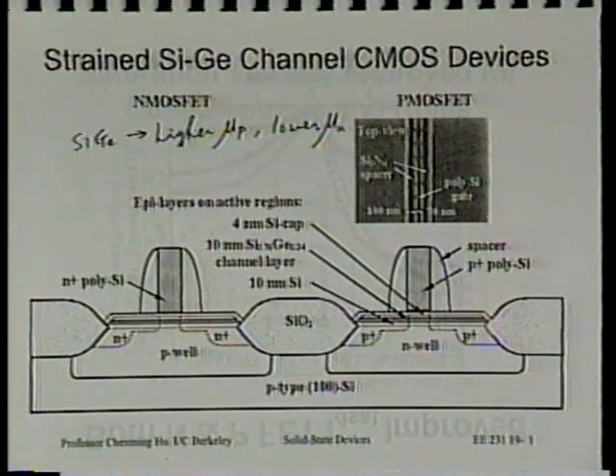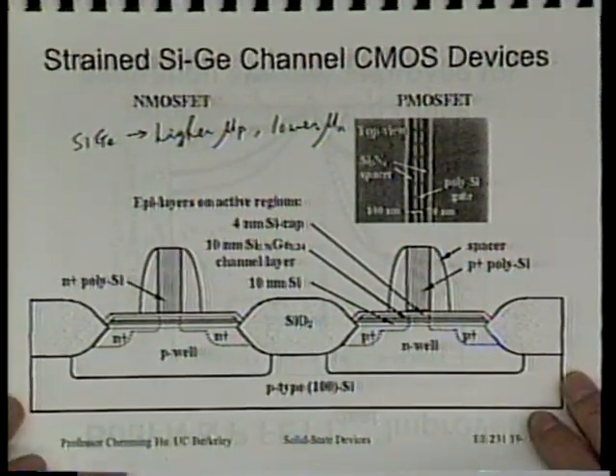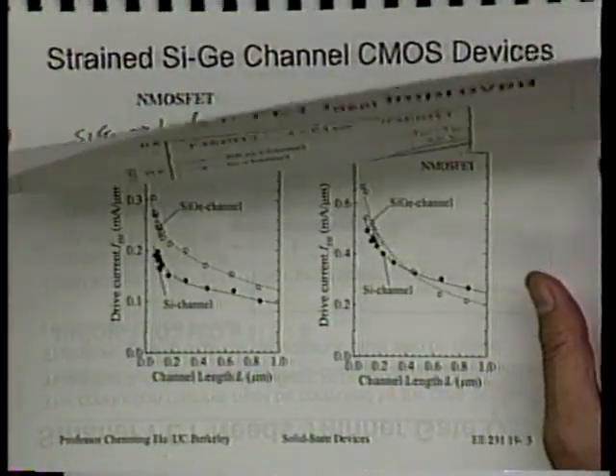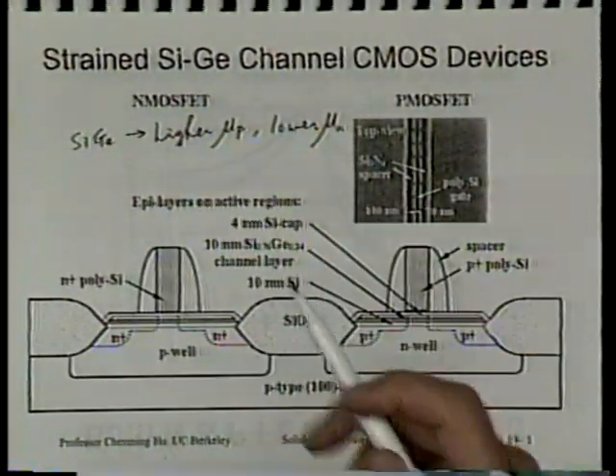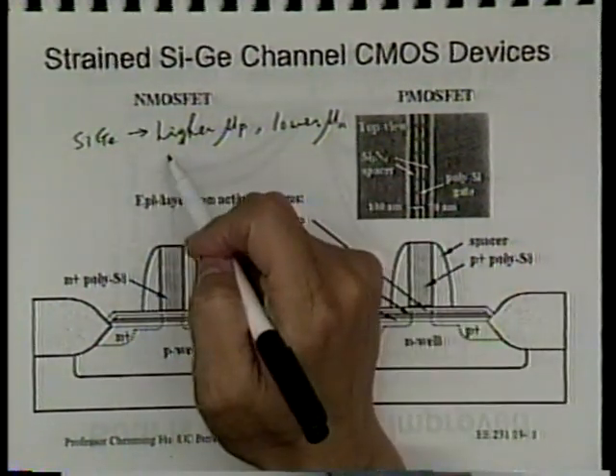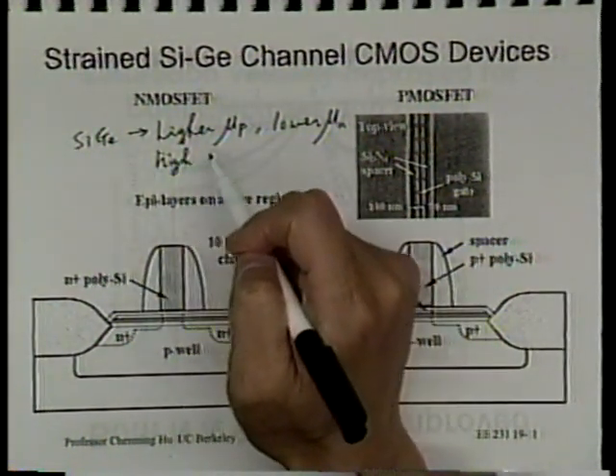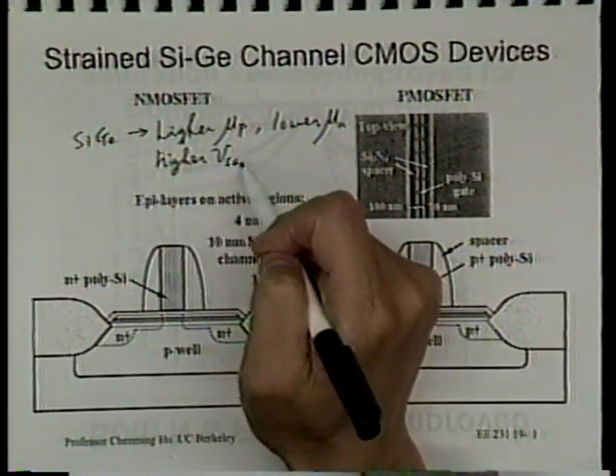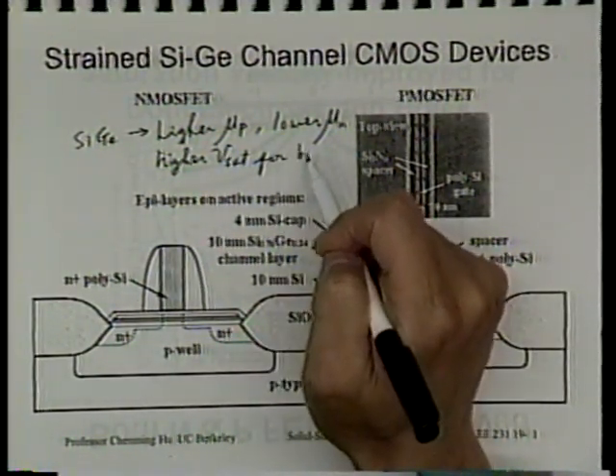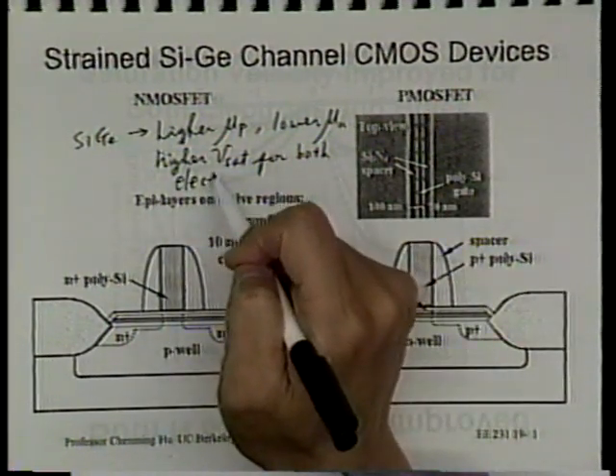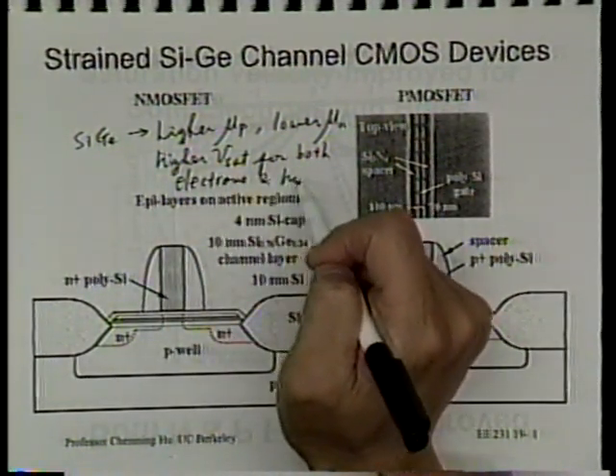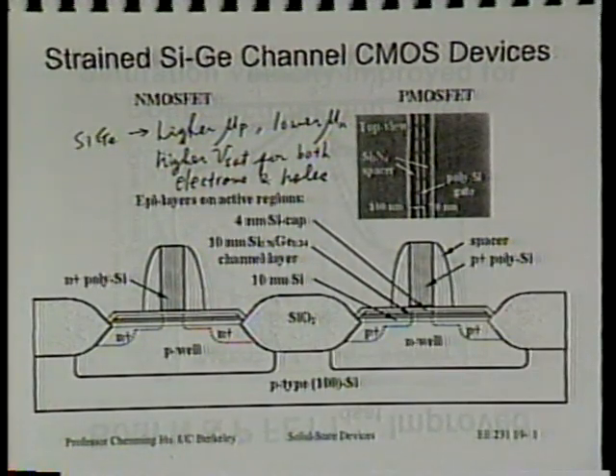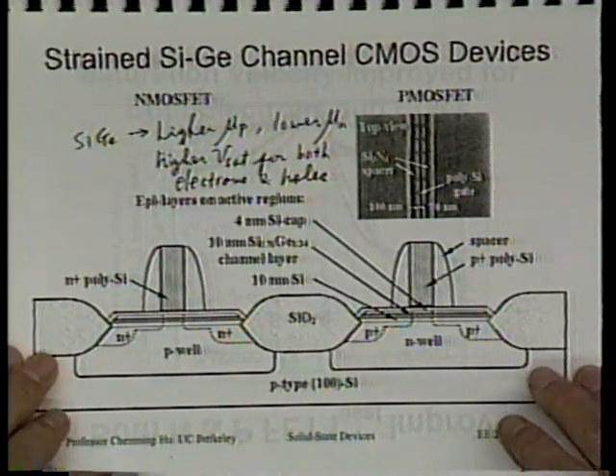Okay. So when you have done that, of course, the process becomes very complicated. Now, what we are proposing is a new concept: we accept the fact that the mobility is lower for NMOS. However, from theoretical study, we predicted we can get higher saturation velocity for both electrons and holes. Because the strain causes band splitting, it changes the scattering, such that we think the saturation velocity can be larger for both electrons and holes.